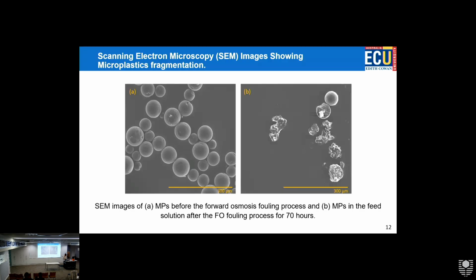So she got another sample from the feed solution, and this is what she observed, that these particles, over 70 hours in a pump that is not a hydraulic pump that presses things and so on, it's just a general centrifuge pump that doesn't put too much effect on the plastics, and it has degraded them to smaller pieces basically. And imagine in an actual water treatment plant or wastewater treatment plant, when they go through lots of pumping and then lots of connections and all that abrasion, stress situation, so these get fragmented to many smaller pieces that are not normally even tested.